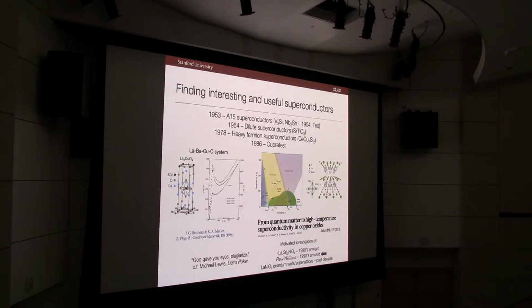And so what Bednorz and Mueller found was that if you did substitutional doping, a little bit like phosphorus doping in silicon, by putting barium 2+ on a lanthanum 3+ site, that you could hole dope the system and find superconductivity, right? At fairly high temperatures, and namely temperatures that are too high to understand via this electron-phonon picture that I previously showed you. So I didn't actually go back and check that this is true, but I could imagine that every year in this colloquium series, at least 1 or 2 talks must have been on the cuprates, right? So it's been an enduring problem and remains so to this day.